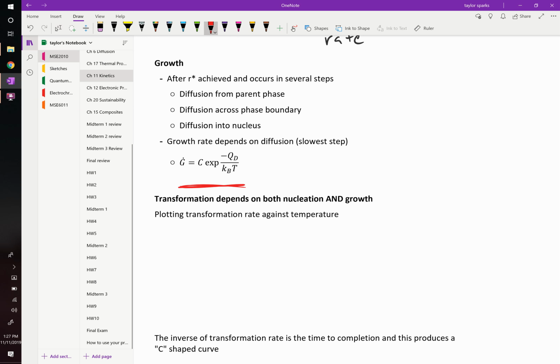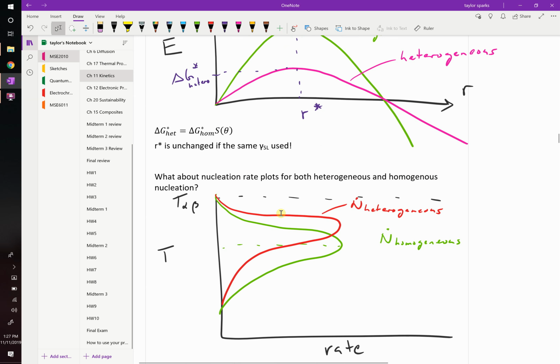Because higher temperatures, so this might be counterintuitive. You might think if I'm only a couple degrees below 0 Celsius, and I do the experiment, it should go really slow because I don't have any nuclei. But remember, that's where you have faster diffusion. And then if you go really, really far below, you might think, oh, great, I'm going to have lots of critical nuclei, but there you don't have good diffusion. So you should see a temperature where you get some maximum rate. I have no idea if you could actually do that on water. It'd be a sweet experiment.